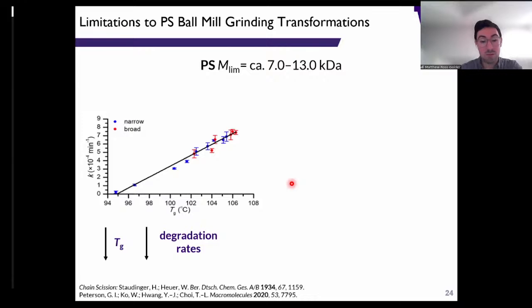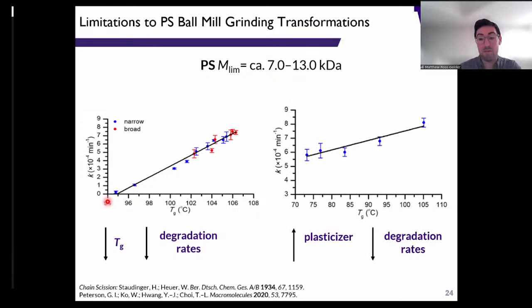And in their work, they were able to show as they start to perturb the glass transition temperature of the polymer, you see a marked decrease in the rate of mechanochemical chain scission. As you increase the amount of exogenous plasticizer that you dope into the material, going from right to left, you also see a subsequent drop in glass transition temperature, which is what a plasticizer will do. And that also leads to a marked decrease in mechanochemical chain scission rate.